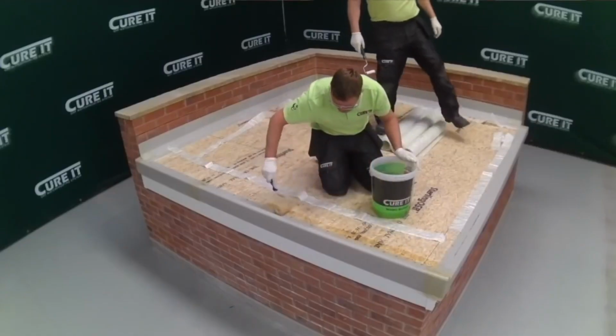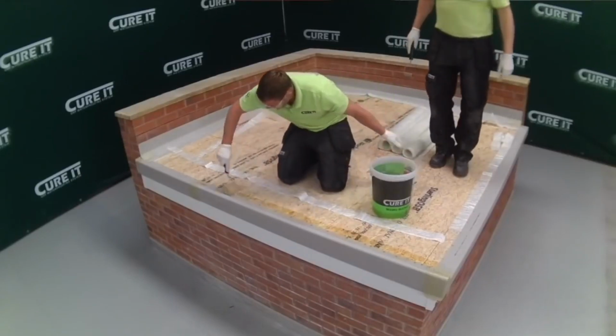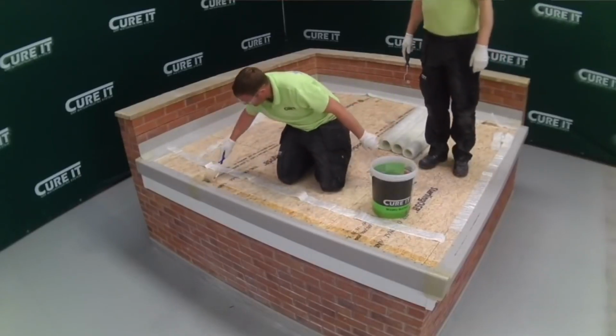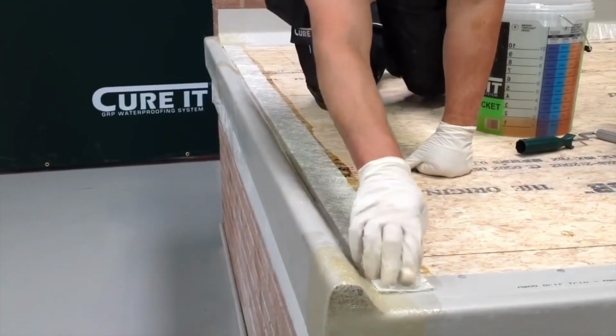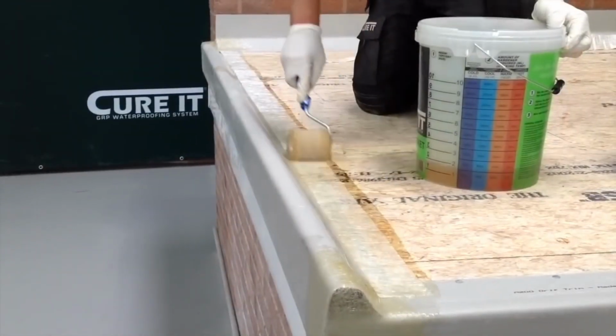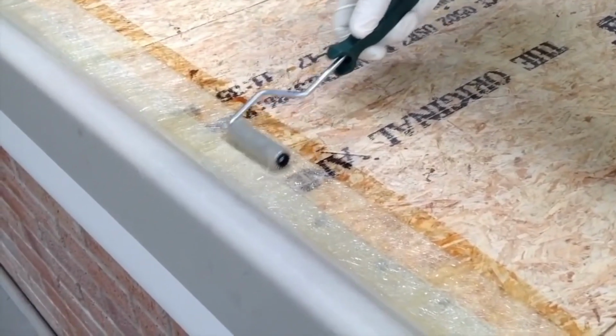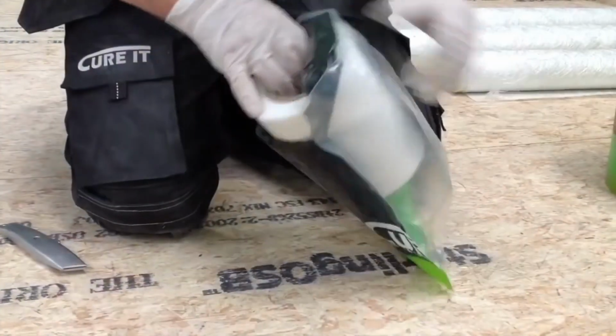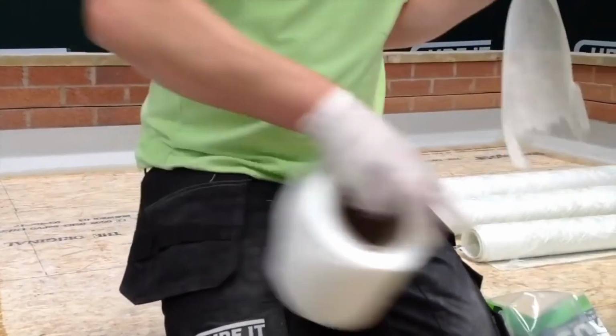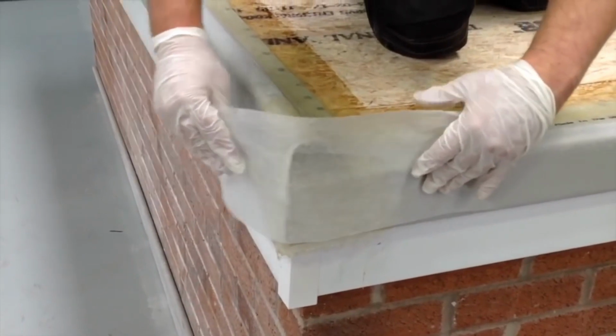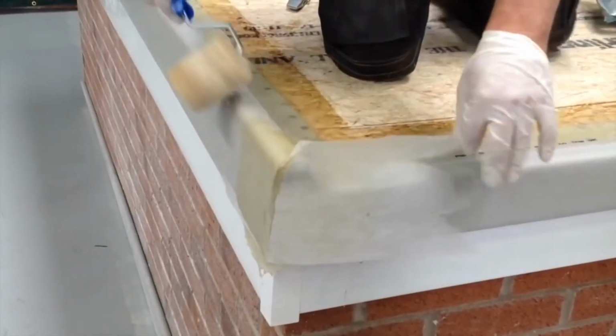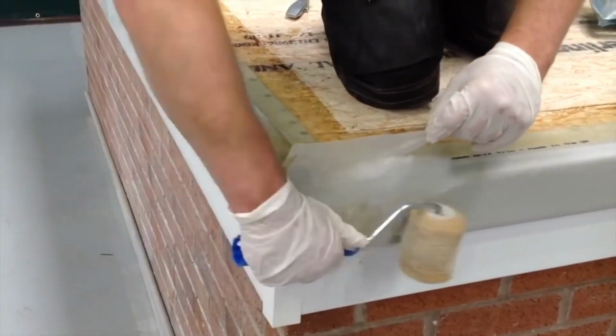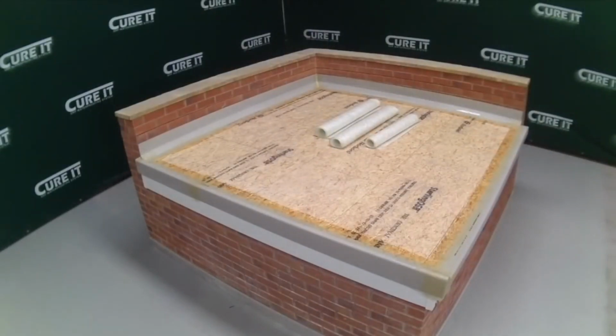The bandage strips can now be applied to where the deck and trim meet. Use a 3-inch roller to apply the resin mix with hardener to the deck and trim area. Lay the strips of bandage on the wet deck and coat with resin. It is important to paddle roll the strips of bandage. While the resin is still wet, offer the detail tissue up to the corner. Use a roller to shape and finish the corner work for a neater corner look. Stage 3 is now complete, and all bandage detail has been applied to the roof.